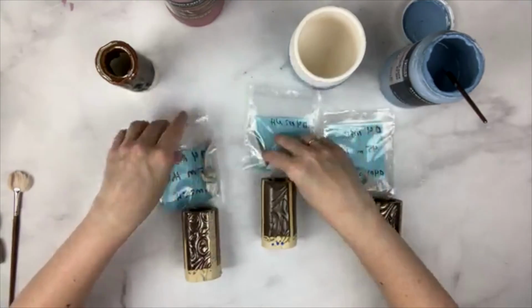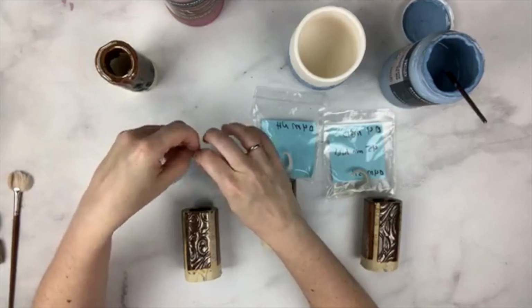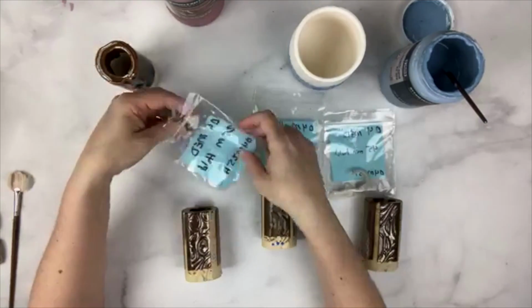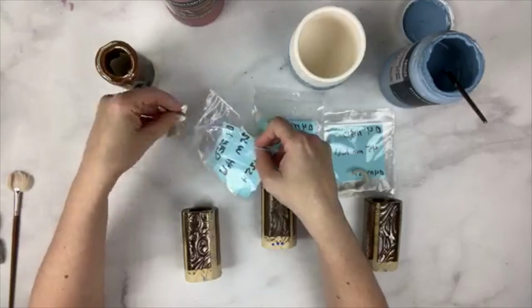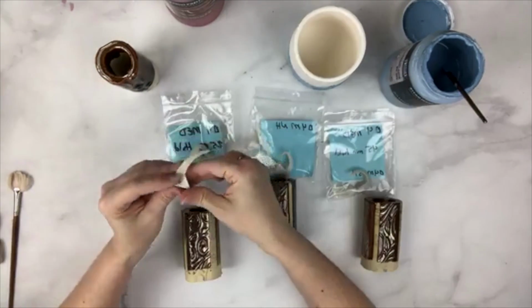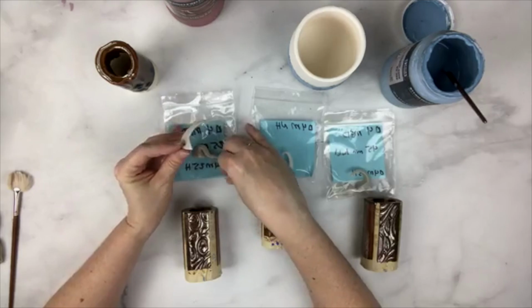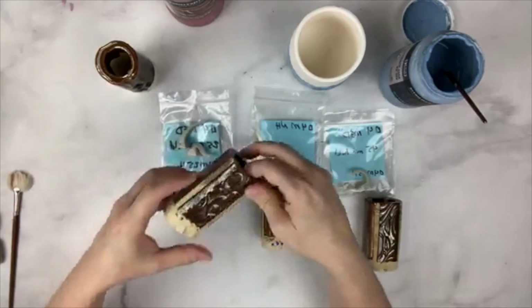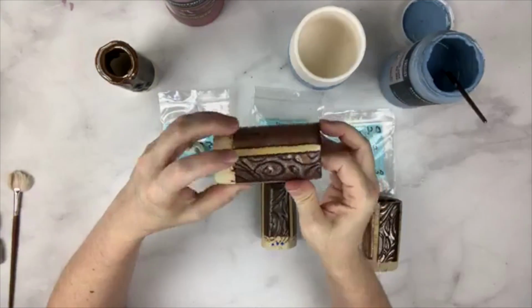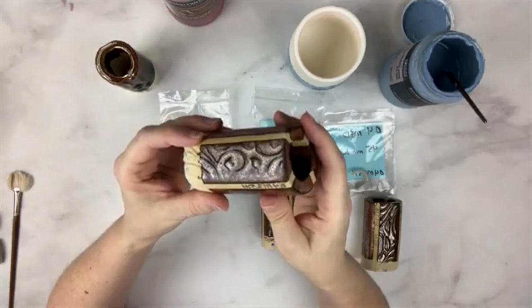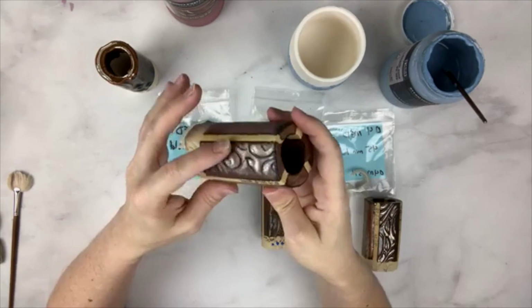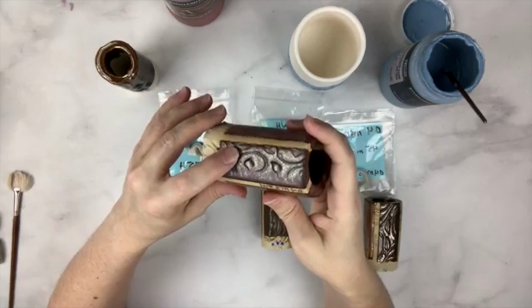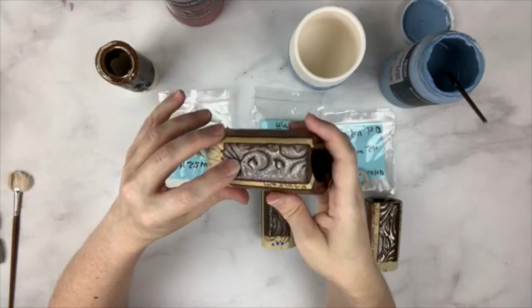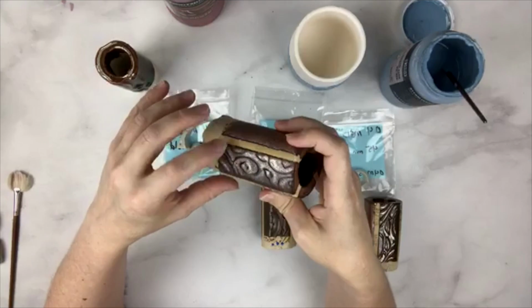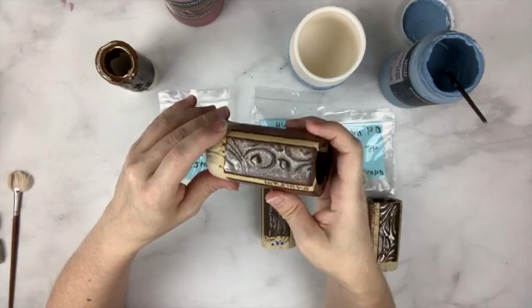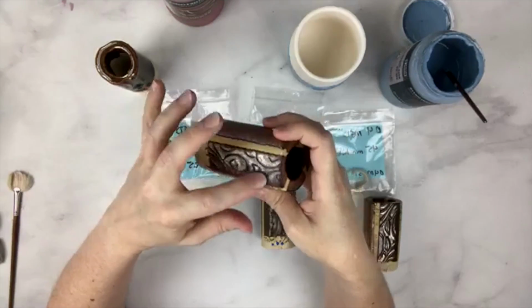So she also fired cone 4 with a 25-minute hold, which when you look at cone 5 is getting pretty close to cone 5 because of that hold. And when we look at the 3 coats, it's starting to develop that patina. It's looking okay. So the hold is pushing it up. So when you have an excessively long hold, like 25 minutes or longer, you are probably getting more heat work than what you are originally targeting. So that's what's happening here.